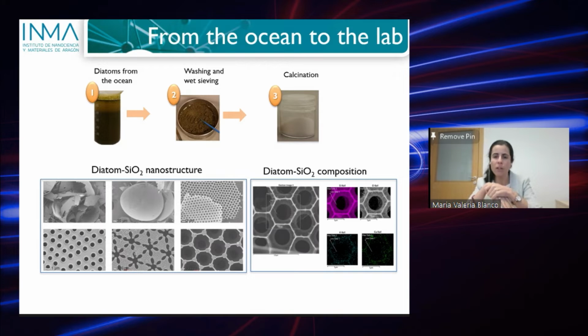And then we do some calcination to get rid of some organic components that the algae have. So the goal is to only have this inorganic part, that is the silica shells of the algae. What you can see in the lower part of this slide is how the algae really look after the calcination process. You can see huge discs of some tens of microns, but normally during the sieving we break them a bit, so you can see that we have some flakes of these